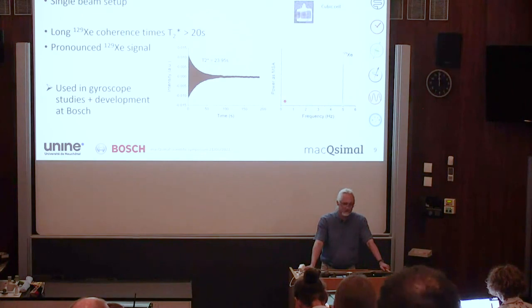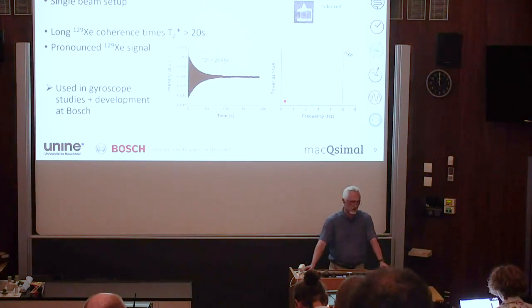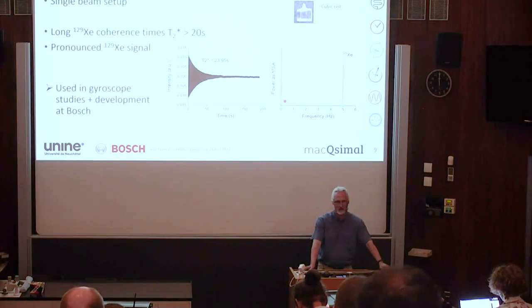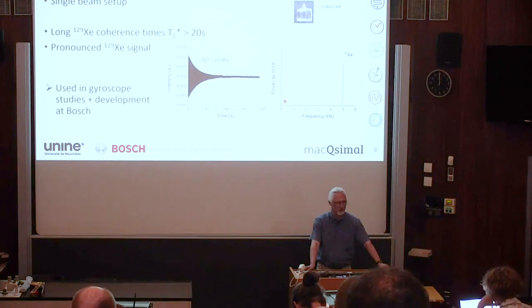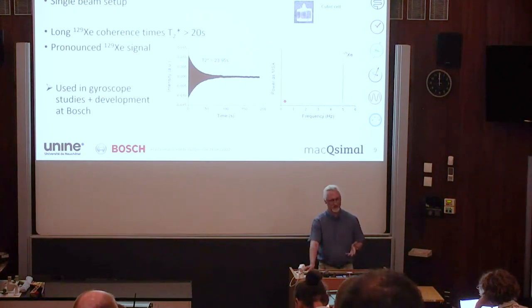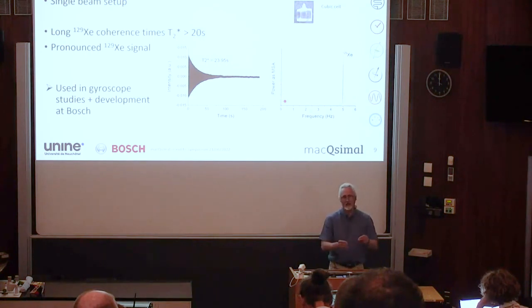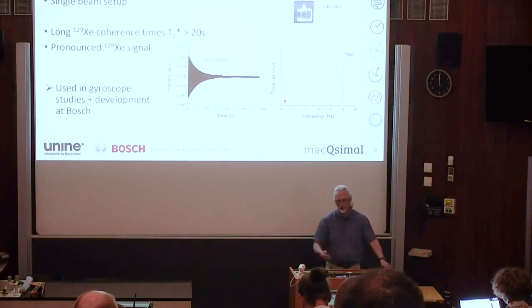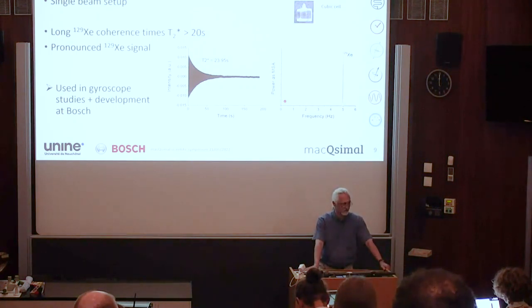Then we have a question from Emmanuel. What would limit T2 star here? The fact that the cell is cubic? I would not expect so. I think the T2 star should probably mostly be limited by the buffer gas fill. If we don't put any buffer gas into the cells, you can easily imagine that the xenon and the rubidium atoms just do ballistic flight inside the cells and bump into the cell walls every millisecond or so. This completely depolarizes the atoms, and that would be a 1 millisecond relaxation time, a T2 time. So we need to put sufficient gas inside so that the relevant atoms for the interaction and for the measurements, the xenon and the rubidium, are efficiently localized and ideally never go to the walls. But they will also decohere due to collisions with the gas and among each other.